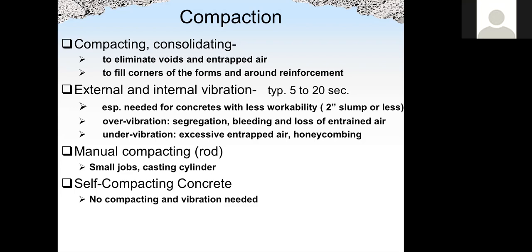We could either use external vibration or internal vibration, depending on the size of the job. When concrete has less workability, for slump less than 2 inch or even less, we need to be careful about fully compacting the concrete. However, if we have over vibration, the concrete may segregate, or so-called bleeding, or even lose entrained air. Entrained air is the good air that ensures the concrete has good durability. So under vibration or over vibration is not good.